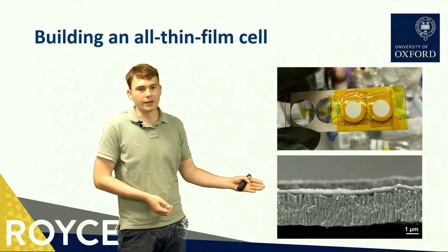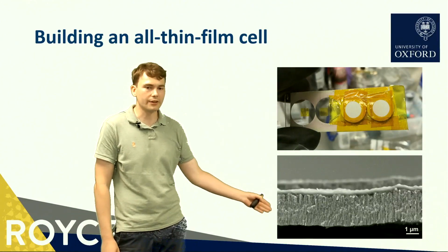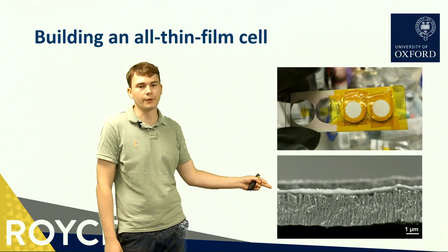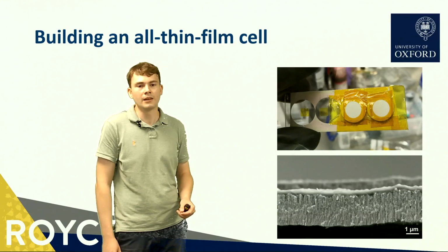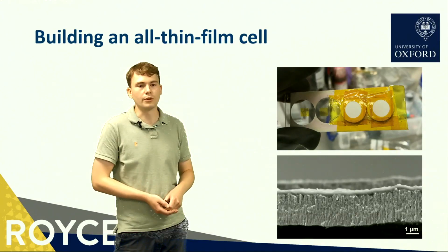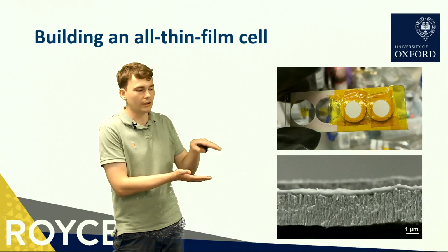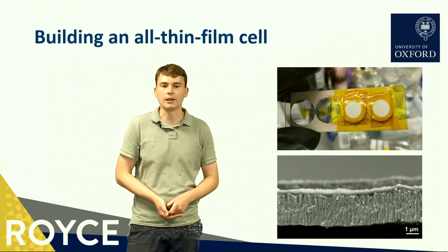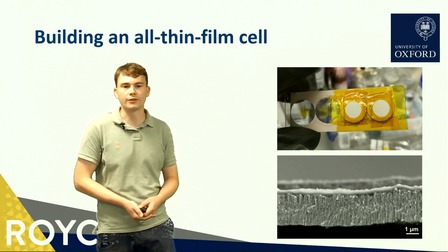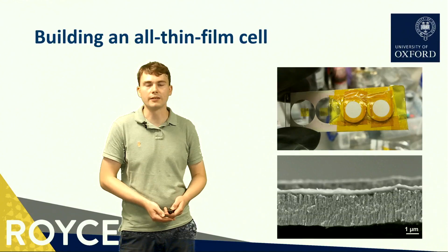And at the bottom I included a scanning electron micrograph image showing an LCO cathode layer that I deposited by magnetron sputtering. And on top of that there's a lithium phosphorus oxynitride electrolyte layer. I included this to show how good the solid-solid contact is when you use sputter deposition. You get a really conformal layer that follows the undulations of the underlying LCO, lithium cobalt oxide layer, and you get better solid-solid contact than you could using bulk synthesis techniques or bulk fabrication techniques.